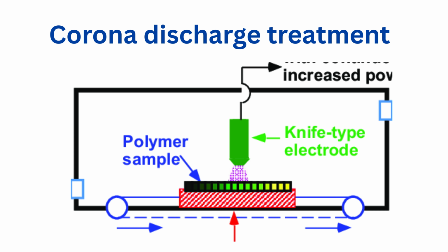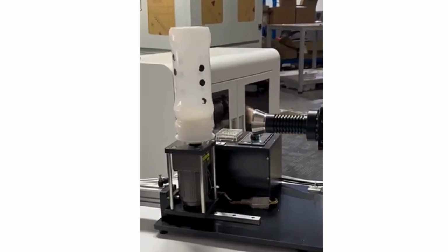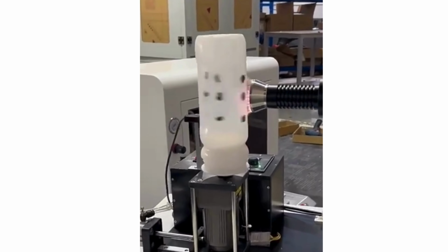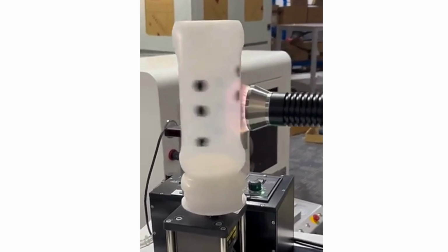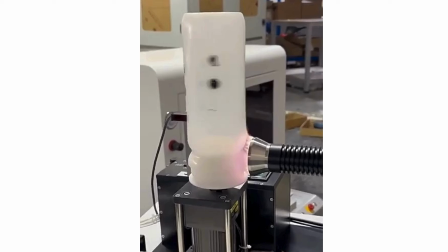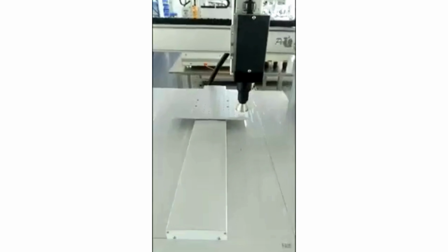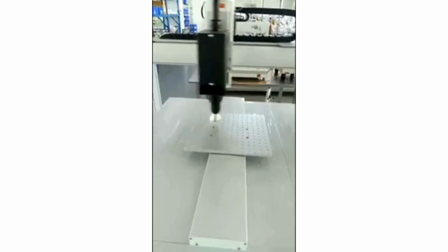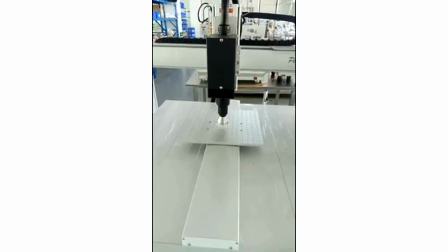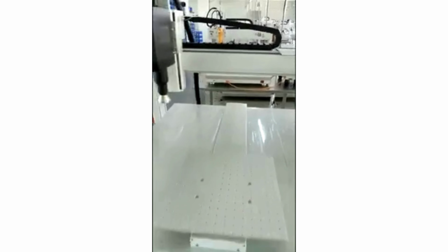The corona discharges have been used industrially for many years to treat polymeric films, fibers, and flat objects. This procedure is used for polyolefins, polyethylene and polypropylene, and some polyesters, polyethylene terephthalate. The electrical discharge between two electrodes is obtained under atmospheric pressure from a high-voltage alternative current.